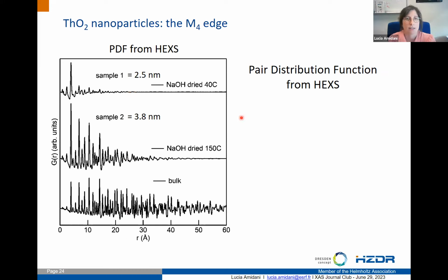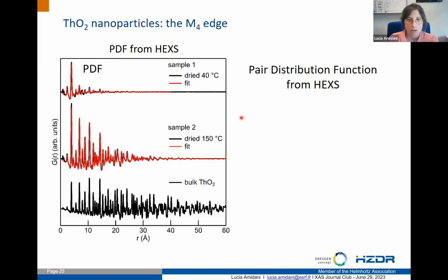The nice thing is that PDF is easy to simulate if we have a structural model. And so we fitted, and we actually got, so here for instance I'm just showing you the fit that we obtained, which I consider very good fits.